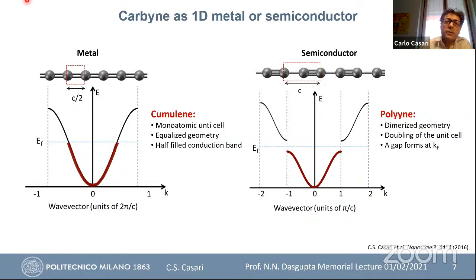For example, you can easily understand the electronic properties, the band structure of this kind of one-dimensional crystal. And actually, if you think about the sp hybridization, you can see that you have indeed two possible organizations of the atoms in this chain. One possibility is to have all double bonds, in a sort of equalized structure. So all the atoms are at the same distance. So the unit cell is one atom per unit cell. And you can easily see that this will lead to a metal, a one-dimensional metal, with a half-filled conduction band. So this structure is called cumulene, and is predicted to be a metal.